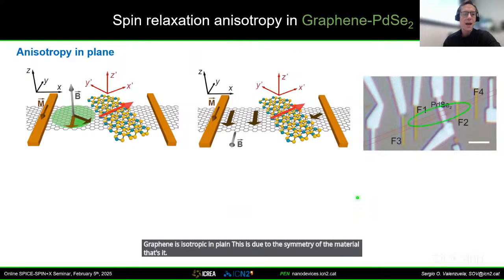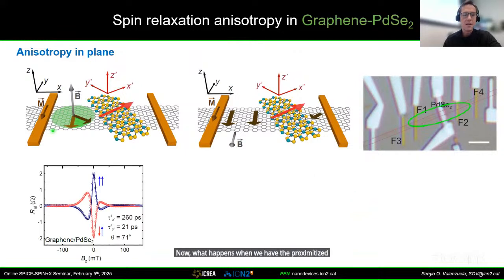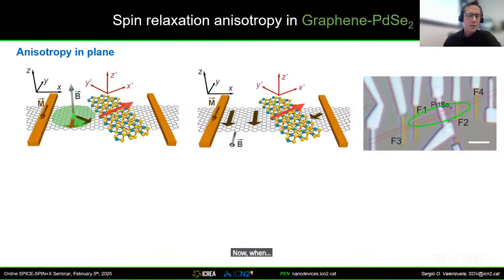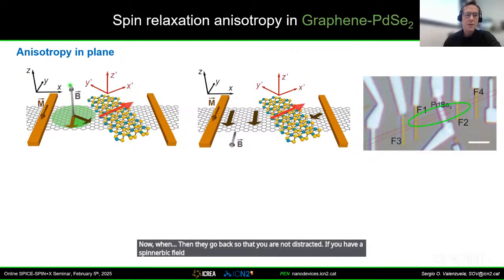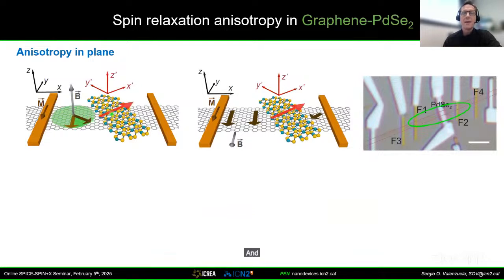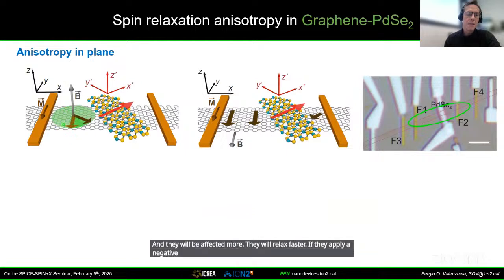Now, what happens if we have the proximitized region with this material? Let me go back so that you are not distracted. If you have a spin orbit field in this arbitrary direction, and we apply a positive magnetic field, the spins will precess like this, and then they will come more perpendicular to the spin orbit field. They will be affected more, they will relax faster. If we apply a negative magnetic field, then they will become more parallel to the spin orbit field, and they will relax in a slower manner.